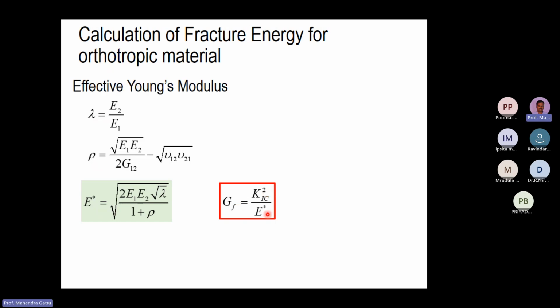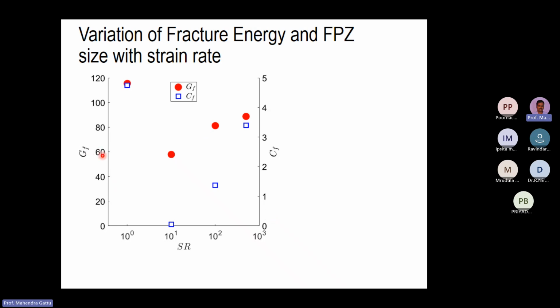Okay. So using this, if you plot the fracture energy, we have fracture energy on the y-axis, and on the x-axis the logarithm of the displacement loading rate. So 10 power 0 is 1, 10 power 1 is 10, 10 square is 100, and 10 cube is 1000, and 500 is somewhere in here. So the red circle is the GF. Initially at loading rate 1 we have a high GF value, then it is reducing at 10, and then again it is increasing and reaches this value. Similarly, the CF, which is the fracture process zone size or the material characteristic length, also follows this trend.